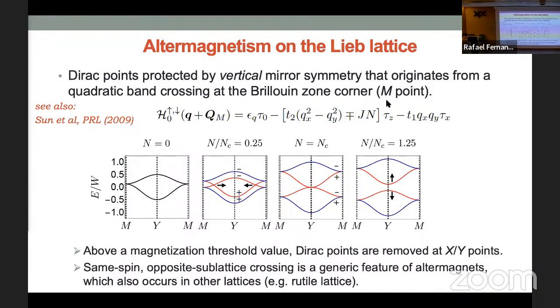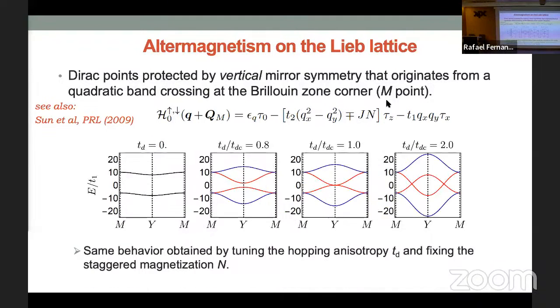Now, this is all without spin-orbit coupling. So our point is that besides the nodal Zeeman spin splitting, there's also another crossing between same spin and opposite sublattice, which is quite generic. And what is nice is that if you now turn on spin-orbit coupling, what happens is that you're going to get that. I also just wanted to say that you can control this: this is the limit where magnetization is zero. You can also start in the limit where the hopping anisotropy is zero, and now it's the other way around, right? So large hopping anisotropy, you get the Dirac points, small hopping anisotropy, you don't.